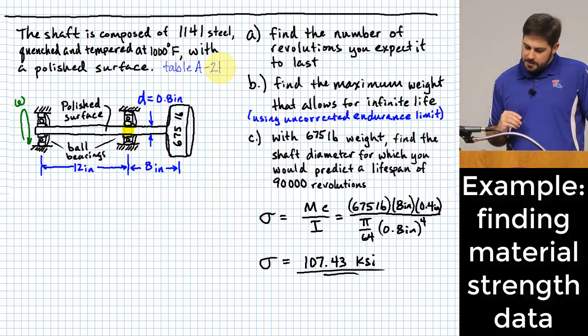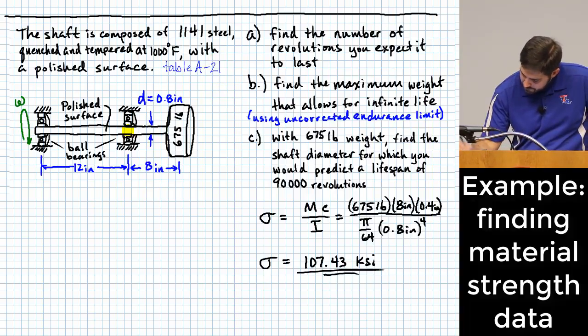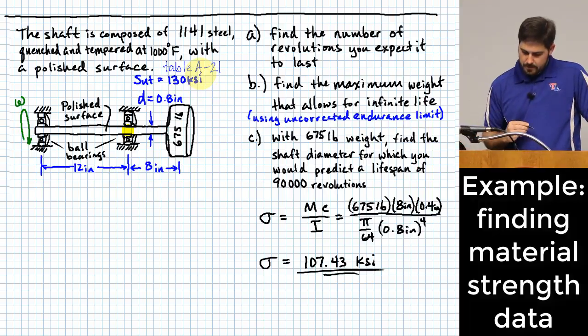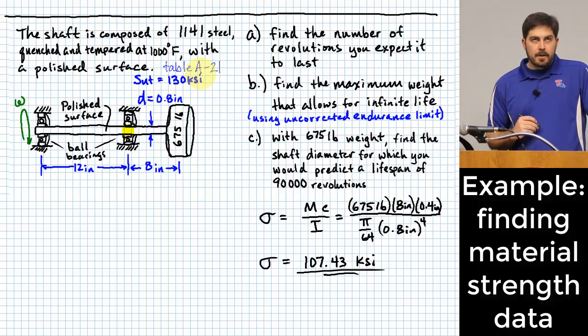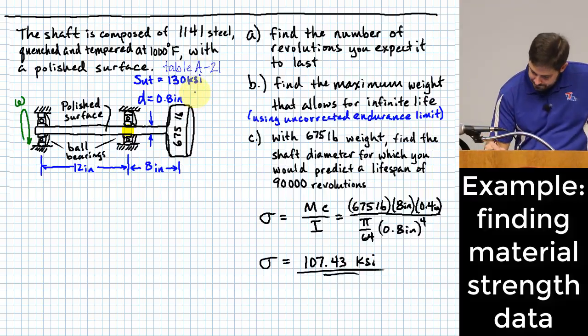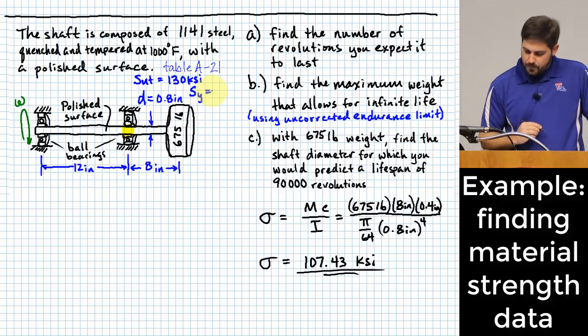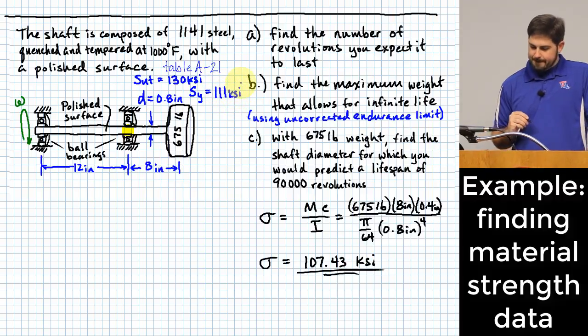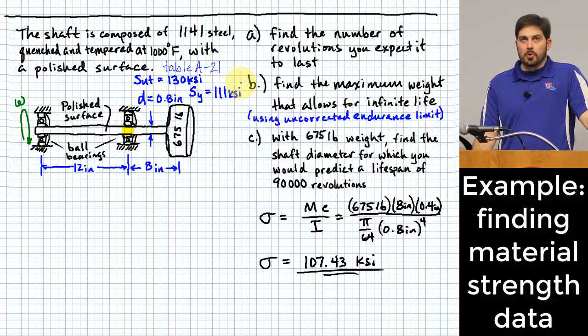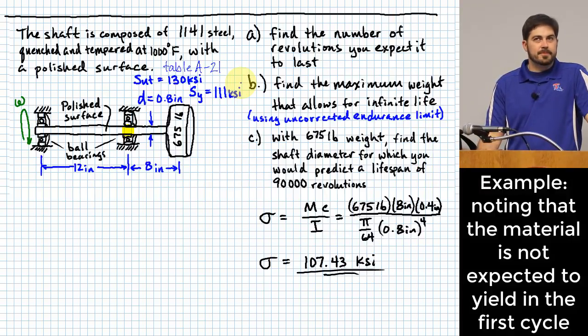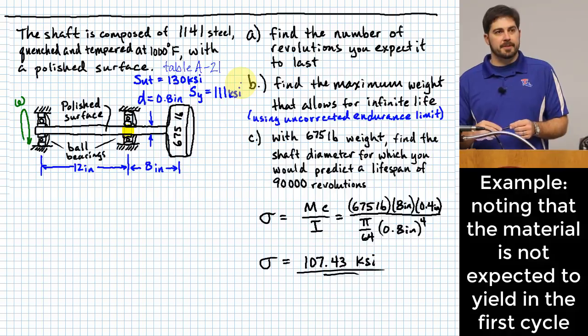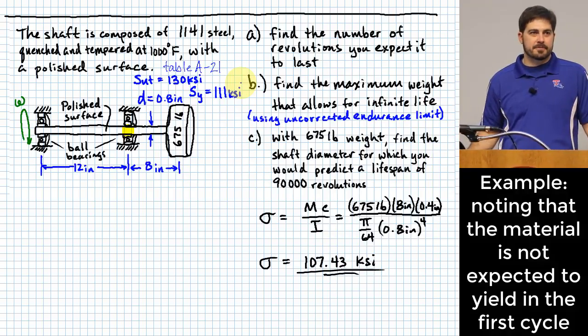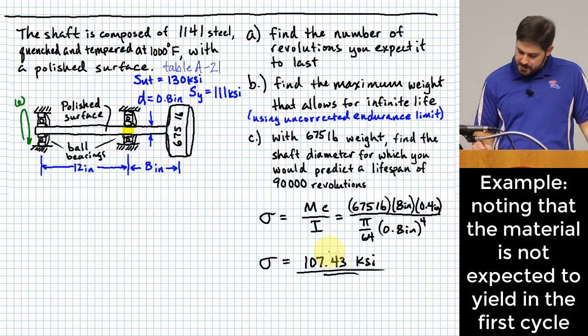This material that's tempered at 1,000 degrees Fahrenheit has an ultimate strength value of 130 KSI. All right. And just as a matter of interest, let me figure out my yield strength value as well. It says it's 111 KSI. So we're right close to yielding it, but not quite. This is actually one of the things that we sometimes check for in these fatigue problems: first cycle yielding. In other words, before you even start cycling it, is it just going to make the thing yield? All right, so what we're saying here is that it looks like we're fairly safe on first cycle yielding.